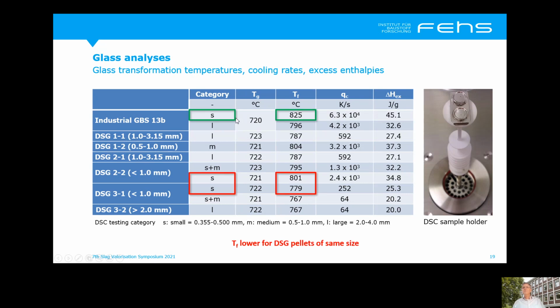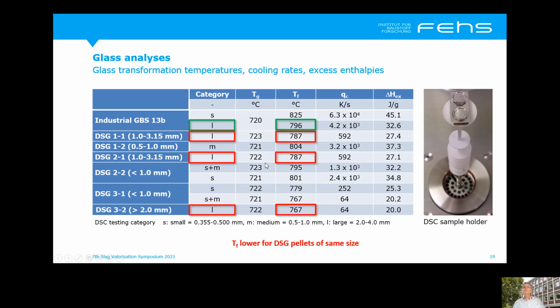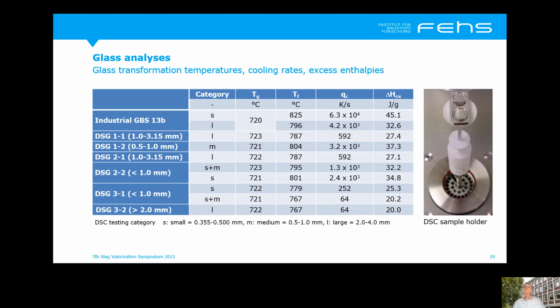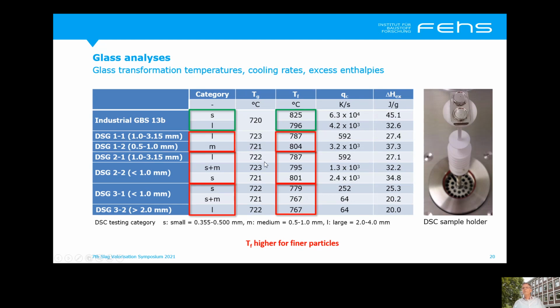First, we look to Tg, the glass transformation temperature under standard conditions, and you can see that there are nearly no differences because the chemistry of all the slags was very similar. The case is another one for the fictive temperature. First, we look to the small particles, and you can see that the fictive temperature for the DSG pellets of the same size is lower. The same effect you can see for the larger particles. For fine particles, as compared to large ones, TF is higher, as well for the wet granulated slag, but also for the dry slag granulated pellets.